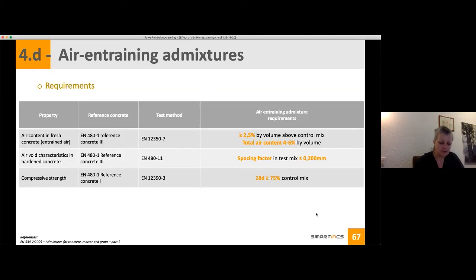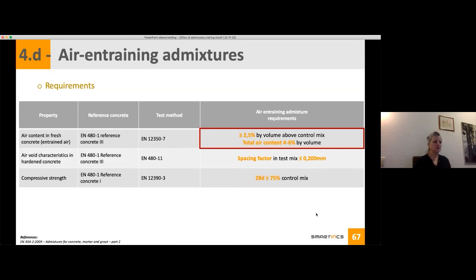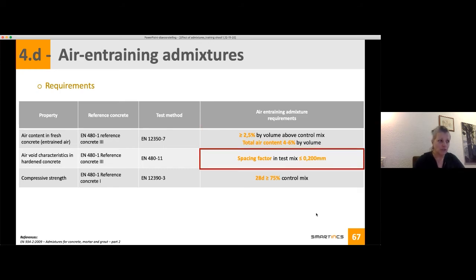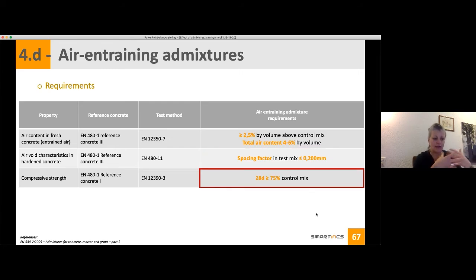If we look at the requirements, the first requirement of air entraining agents is, of course, the air content that you would bring inside your concrete mix. It should be more than 2.5% compared to a control mix, but the total air content should be no more than 6% by volume. One aspect that is very important is the spacing factor. The distance between two air bubbles should be less than 0.2 millimeter. And I mentioned earlier that air content will have a direct impact on your strength. So here you will have more air, so you should expect lower strength, but the strength at 28 days should be at least 75% of your control mix.